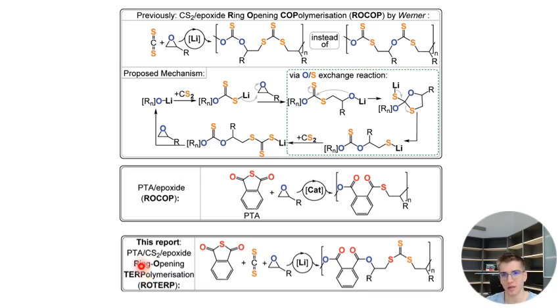But essentially it's just two ring opening copolymerizations combined, where you add the cyclic thioanhydride, the CS2 and epoxide, and the oxygens and the sulfurs sort. Yeah? So you generate these diester units which alternate with trithiocarbonate units. Yeah? And the trithiocarbonate units here, they are next to CH2 groups, and the esters, they are next to the substituents here. Yeah, we also call this a head-to-head, tail-to-tail selectivity, which I will explain further. But it essentially originates from the fact that the epoxide is always selectively ring opened, or nucleophilically attacked, at the less hindered CH2 position.